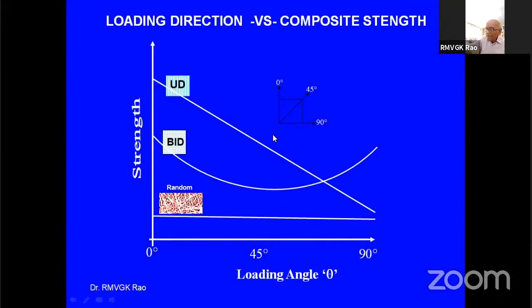This slide is very interesting. There's a standard slide available, but the important point is one thing: to test the material in line with the fibers, naturally, it gives maximum property. But if you test it transverse, at 90 degrees to it, what happens? If it is unidirectional, in the transverse direction, you see the unique curve, strength versus loading angle. So it is maximum at 0 degree. That means along the fibers. It is least, it drops down so drastically when it goes to the 90 degrees.